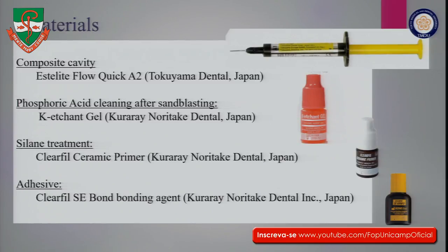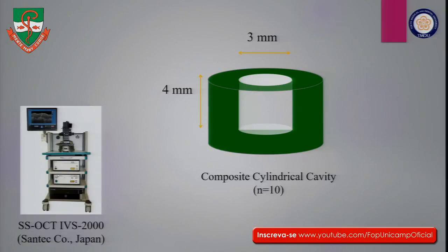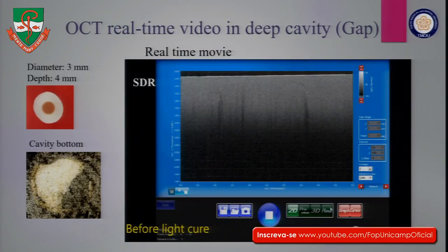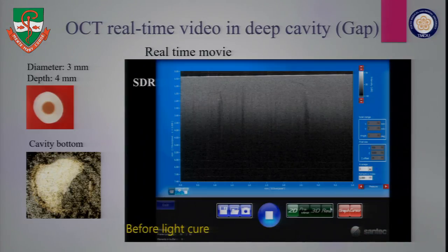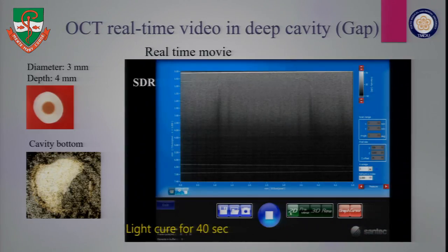Then we applied the best bonding procedure to the cavity made by the composite resin. We use the composite resin cavity because a 4 millimeter deep cavity cannot be created, so prepared, in the tooth. So anyhow, we could obtain a very good bonding and we fill it. And this side is the bottom of the cavity. This is one of the bulk fill composites. Then we apply the light. You can see the gap is propagated here during the light curing.